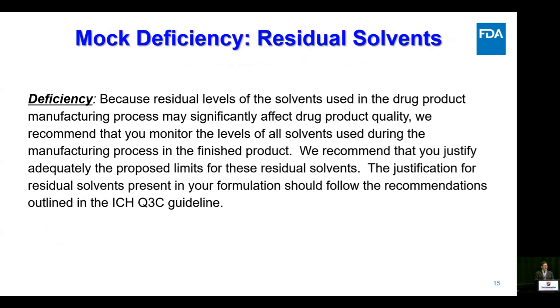Also, there are lots of organic process solvents used during the manufacturing process. Another example of a deficiency is related to residual solvents. Because residual levels of solvents used in the drug product manufacturing process may significantly affect drug product quality, we recommend that you monitor the levels of all solvents used during the manufacturing process in the finished product. We recommend that you adequately justify the proposed limits for these residual solvents. The justification should follow the recommendations outlined in the ICH Q3C guideline.